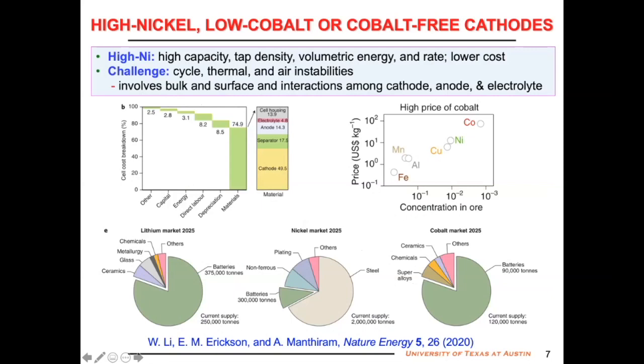Nickel can go all the way to 4+, so we can get much higher capacity with nickel than cobalt. Also, fortunately, when we synthesize compounds with high nickel content, we get high tap density. That's good for high volumetric energy density. Even though nickel does not become metallic because we are operating with the eg band rather than the t2g band, it is still highly covalent, so you can get good rate capability. In the battery, about 50% of the material cost is from the cathode, and in the cathode, cobalt is the most expensive, and cobalt also has less supply compared to nickel, so there is a lot of interest to get rid of cobalt and increase nickel, so that can also lower the cost.